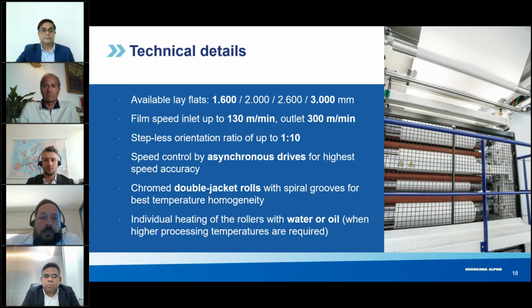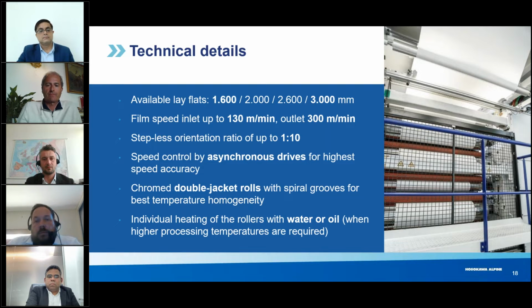Our MDO is available in several widths between 1.6 and 3 meters. The film speed inlet could be up to 130 meters per minute. The outlet could be up to 300 meters per minute. The stretching ratio mechanically is possible 1 to 10, but for PE films, we say in general 1 to 5 is the most common stretching ratio. The rollers can be controlled asynchronously for highest speed accuracy, and the MDO rollers are chromed double jacket rolls with spiral grooves for the best temperature homogeneity. The individual heating of each roller is possible, or it's standard. You can choose between water or oil.